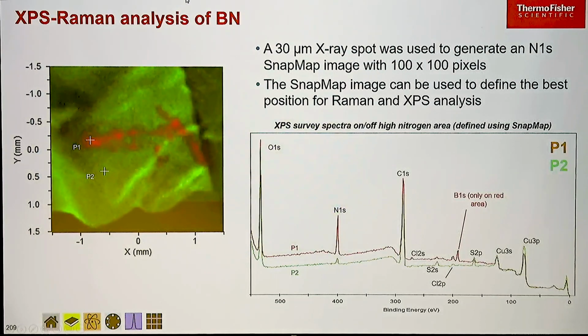But the question is, is it the right form of boron nitride? Is it cubic or is it hexagonal? We want the hexagonal form to be able to say that it is at least a 2D material, and they just need to refine their synthesis process. So we've got the snap map, and then we can choose analysis points. So one on the area where the nitride is, one on the area where the nitride isn't. In the area where there isn't any nitride, we don't see any boron. We only see boron where the nitride was detected. So we've got a pretty good idea now that we've got boron nitride there.